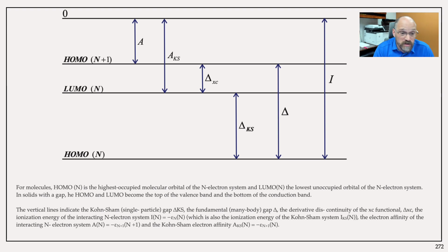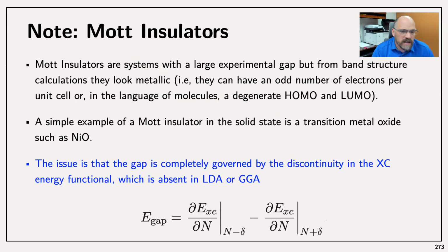One example is the Mott insulator. Mott insulators are only insulators due to correlation, the exchange and correlation effect. In the case of the Mott insulator, it's an insulator, as the name says, but the band gap is solely due to the exchange and correlation piece of the DFT problem. So if you were to pick a Mott insulator that you want and do a DFT and LDA calculation, you will find a metal. That's basically what it says. So that's interesting to know.